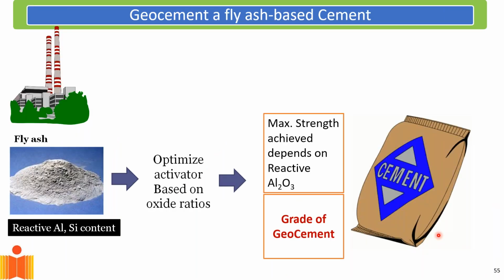And the whole point here is to get a source of silica or alumina. Currently, the cheaply available sources of silica and alumina are fly ash and slag. And we basically activate it using alkalis. One can optimize the activator ratio, and we can start now making these cements, which are derived completely from waste, and we are getting away from limestone. So basically, the carbon footprint of this material is very, very small. So this is also a concurrent parallel development that is taking place, which perhaps may see a larger role in the future.